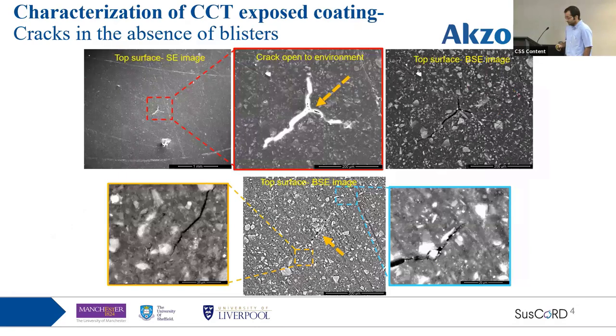Now I started characterizing the exposed panels, the panels which were exposed to the cyclic corrosion test. What you can see here is that this low magnification image shows no evident blister, but we can see crack formations on the surface. And there is also a crack here. This was on the samples exposed for 6 months and also on the sample exposed for 4 months. So the cracks start on the surface of the samples and then propagate. These are the propagation tips of the cracks into the coating, and then they propagate through the coating.